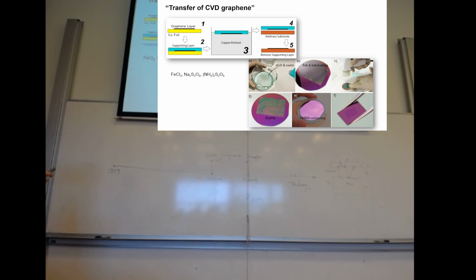say. Basically what people used at the time was some kind of iron chloride, sodium persulfate, and things like that. These are just very mild copper etching agents. It etches copper at a very low rate. So over a few hours, you'll get a very continuous film of graphene. Of course, there is a protecting, supporting layer on top of that. Graphene is reported to have a very, very strong Young's modulus, but yet it's very fragile. So that's a little bit contradictory.